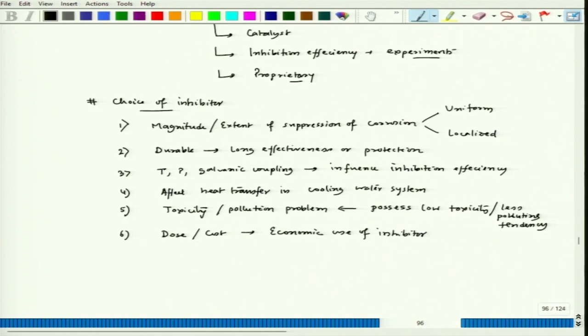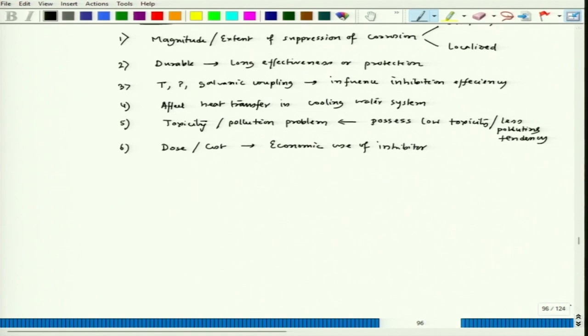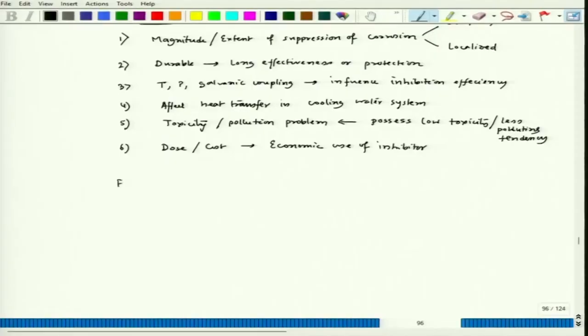Fine. Now we have been talking about inhibition efficiency. Now we can actually calculate inhibition efficiency, and that should be calculated on the basis of experiments. So there could be two ways one can do experiment. One is you mix inhibitor with the electrolyte where that particular metal will be exposed to. You dip the metal, wait for some time, take it out and see the weight loss. In one case, you don't add inhibitor and then see the weight loss for a particular specific time. And then you have two corrosion rate values. So one corrosion rate we can consider to be blank. That means where we have not used any inhibitor, the other case which is inhibited. Now the difference divided by the corrosion rate without inhibitor, we can get the efficiency. So efficiency of inhibitor